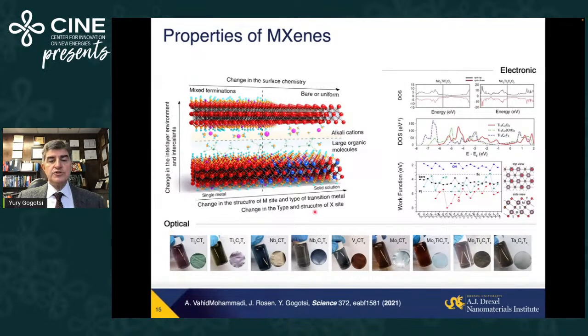And nanotechnology is not really about making things small. It's about controlling behavior, composition, properties at the nanoscale. Just to give you an example, titanium 2C is green in reflection, red in transmission, just like gold nanoparticles, but without gold, like colloidal gold particles. But add one layer of titanium and carbon, make titanium 3C2, and the situation changes. It becomes actually green in transmission and kind of violet in reflection. Those are complementing plasmonic colors of the materials.